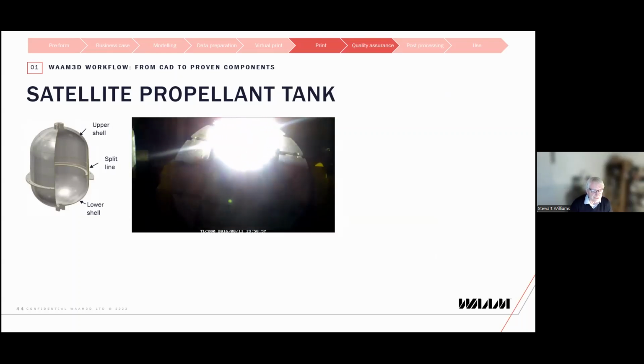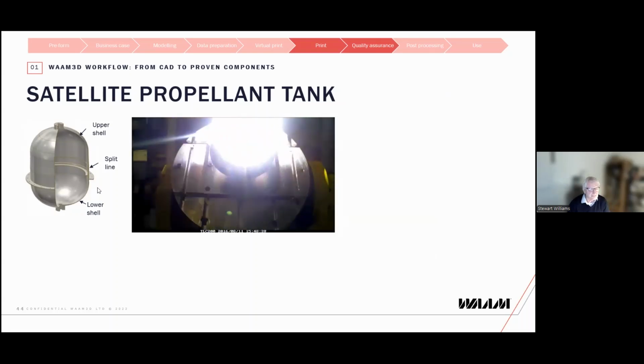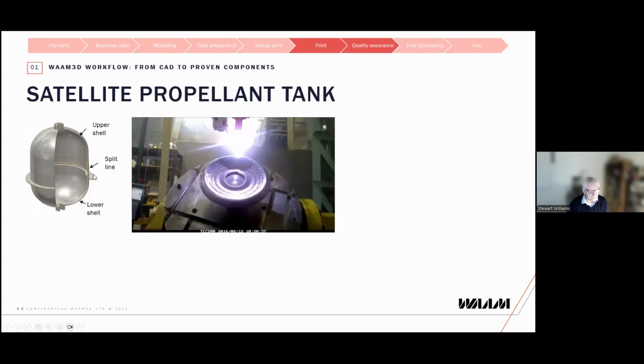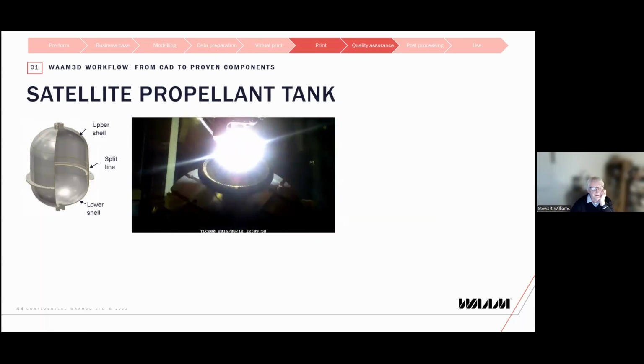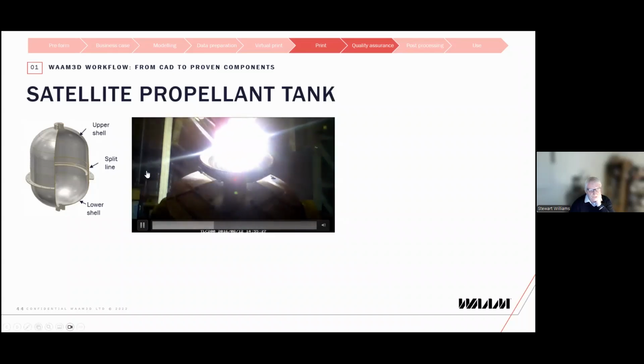This is an early example that we took through for qualification. This is a similar kind of thing. This is a satellite propellant tank, and this is normally made from a forging this thick, around 35 millimeters thick. And what we're doing is producing a near net shape preform. And you can see the process here. We're operating in a tent for an argon environment for this particular case.